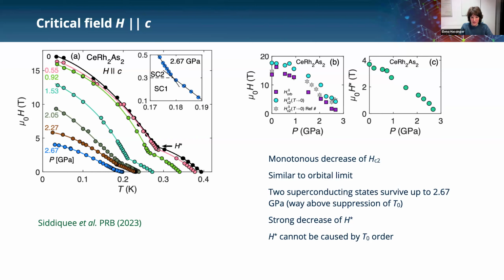And in this superconducting state 2, so for the data above the kink, above H star, we can fit this curve with a normal orbital limit, so pure orbital limit. And so the extrapolation to zero temperature is the orbital limit, and this strongly decreases. But you can also analyze the orbital limit by taking the slope here near TC, and we compare the two, and this is shown in this graph. So the orbital limit that we take from the slope is in violet, and the orbital limit we get from the data in the zero temperature limit is the blue one, and they track each other quite nicely. And so that's why we think that this suppression of the critical field is only due to a suppression of the effective mass, so a decrease of the correlations.